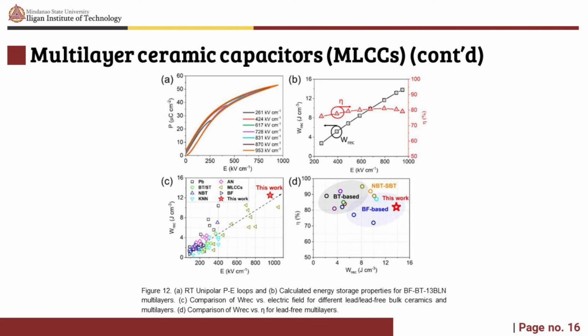Bismuth is reduced at the platinum-dielectric interface by residual carbon from the binder. The reduction of bismuth is enhanced by the formation of an alloy with the platinum, driven by the increase in entropy through mixing. The unipolar PE loops and energy storage properties of BF-BT-13BLN multilayers are shown in